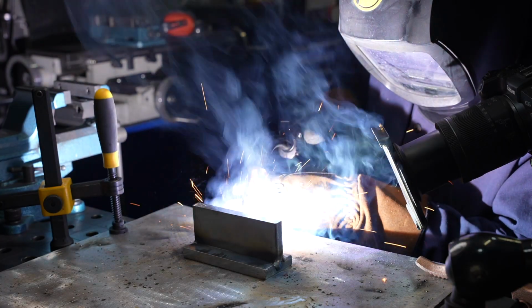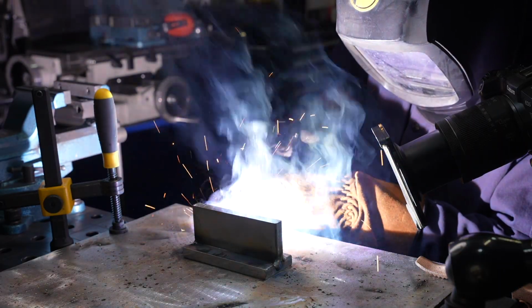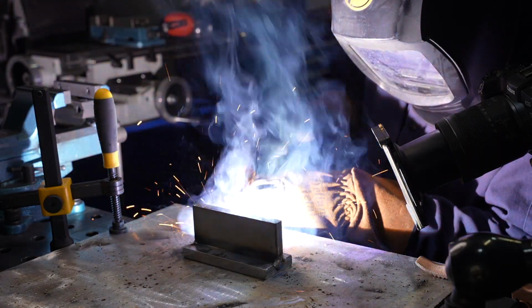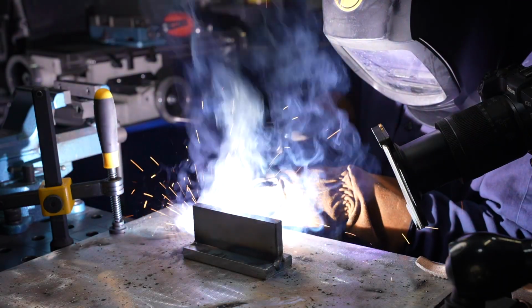Now notice that slag following right behind your weld pool, and it's not too bad to actually read the weld puddle. It reminds me a lot of 7018 where that slag follows right behind, but this slag freezes really fast, which is one of the things that's pretty helpful in the vertical position. I'm holding that little bit longer stick out once again, and that seems to work.